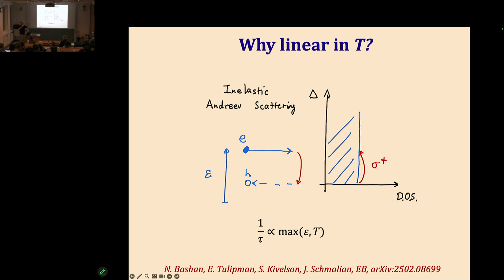But statistically, there would be a constant density of states for these puddles over a whole energy range, including 0. There's a finite probability to find puddles where the n and n+1 states are as close to 0 as you want. And now we have an electron from the metal that scatters off this puddle, and that scatters off this basically constant density of states. This is an inelastic Andreev process, meaning that the incoming electron is actually reflected as a hole, adding one Cooper pair to the system, which costs a finite energy. And we have a constant density of states to have this process.